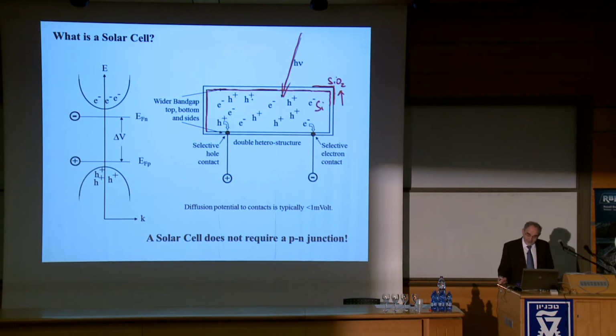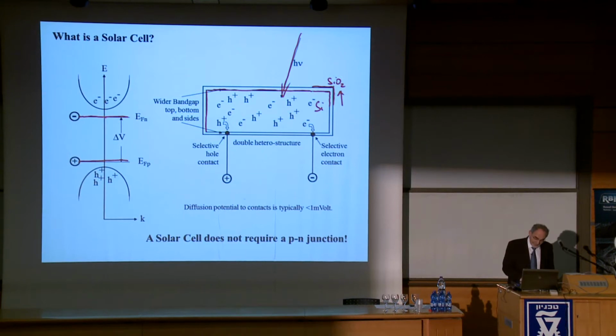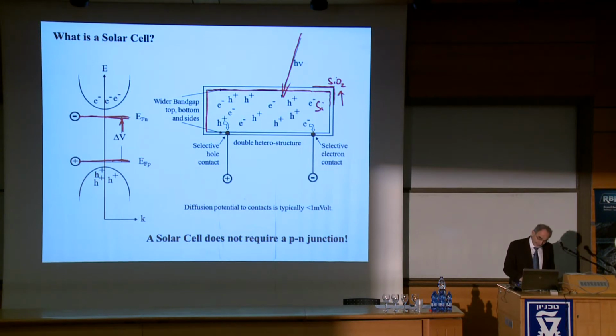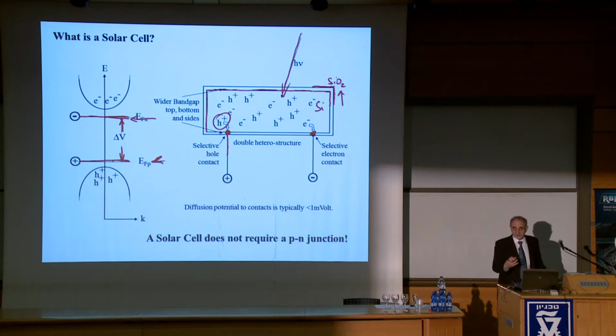So you are trying to build up a very high density gas of electrons and holes. Why do you want a high density? The density relates to free energy. So in solar cells, you have two free energies, one for the electrons and one for the holes. These are separate free energies, and they are separated by a certain voltage. Now, if you have an electrical contact that only sees holes, then you will see this voltage. And if it only sees electrons, then you'll see the other voltage. And so you have two Fermi gases at two different chemical potentials available, and so you have the possibility of extracting electricity at a certain voltage.